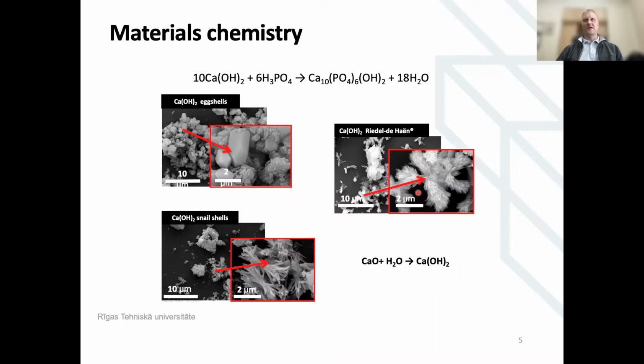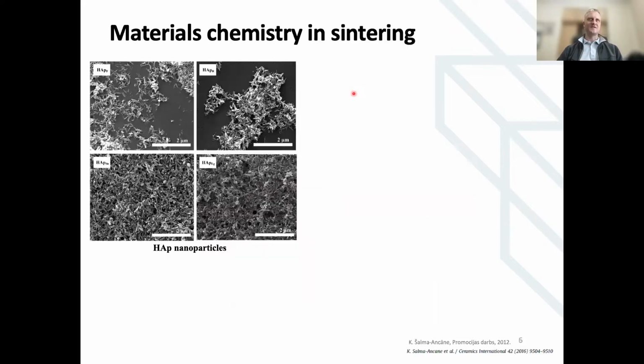Of course, taking into account the reaction, anyway, it will dissolve to form the hydroxyapatite. We don't care much about that. And we do the synthesis. So here you can see on the left side hydroxyapatite synthesized from several sources: from eggshells, snail shells, and also 2 commercial calcium hydroxides. All of them look the same. The nanoparticles are needle-shaped, about 20 to 50 nanometers in diameter and about 200 nanometers in length. No big difference. But then, as we aim to give some mechanical properties to the material, the first thing